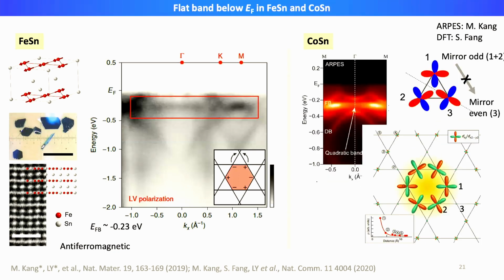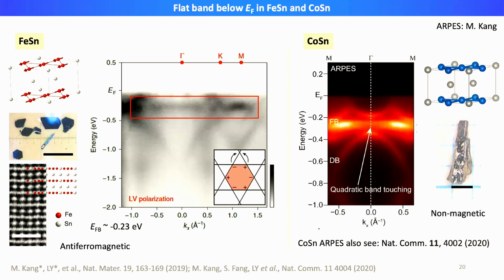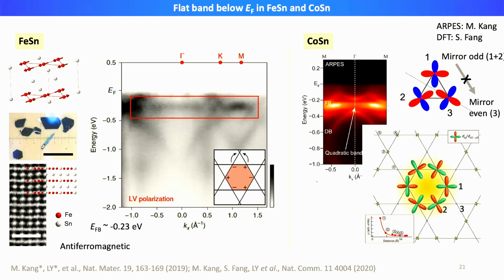In the case of cobalt tin, it's non-magnetic, while iron tin itself actually has antiferromagnetic order for the iron atoms. In the non-magnetic case, we have a much better first principles understanding of the wave function in the system. So here I want to show you the calculated real space Wannier function of the flat band states in cobalt tin, and you can think of this as a proxy for the real space eigenstates of the flat band. What you can see here is a set of rotated d orbitals on this hexagonal loop, very similar to the real space eigenwave function we've seen earlier.